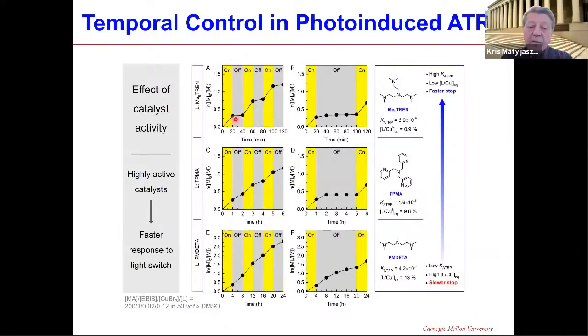So here is a really very fast switching, 20 minutes on and off, and you could see that for hexamethylated TREN, the most active ligand, the reaction stops pretty fast in the dark period. For TPMA, it doesn't, unless you go to a longer off time, and in that case, you could see that the reaction eventually stops. If you go to PMDETA, practically there is no stopping of this reaction. You would need to wait probably more than 20 hours to stop it. So this is related to the amount of copper 1 and the equilibrium condition. Here is less than 1% copper 1 or 99% of copper 2. Here would be 10% of copper 1, and here would be 13 or 15% of copper 1.